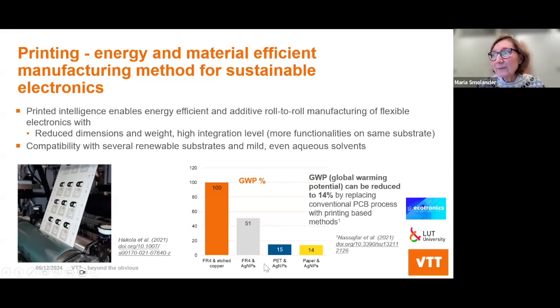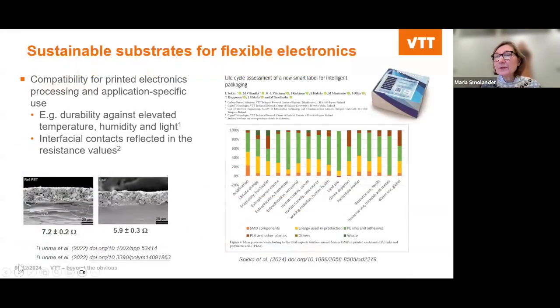And then further, if it's possible to replace the FR4 with flexible substrate, either polymer-based PET or paper, the global warming potential is reduced even more, and it goes down to 14–15% of the original, which is of course very nice. And yeah, indeed, the benefits, which I didn't mention earlier, in addition to compatibility with several substrates, it is also beneficial that you can quite often work with mild solvents, which is very nice from the work safety point of view, of course. Yes, and okay, the process is pretty good from a sustainability point of view.